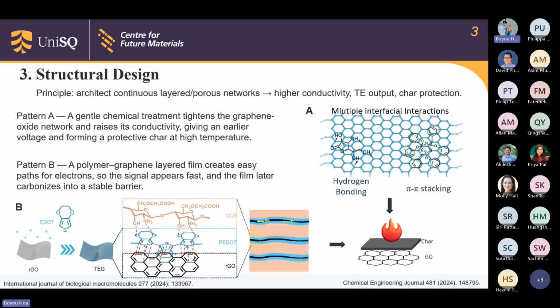From this slide, I'm showing some research work using structural design methods. The idea behind these studies is simple: make continuous layered or porous networks. This raises electrical conductivity and gives a strong heat-to-voltage signal, with a protective layer. In pattern A, researchers begin with a graphene oxide film and use a mild chemical treatment that partly reduces the sheets and tightens their contact, which raises electrical conductivity and strengthens sheet-to-sheet stacking, like hydrogen bonding and pi-pi stacking.